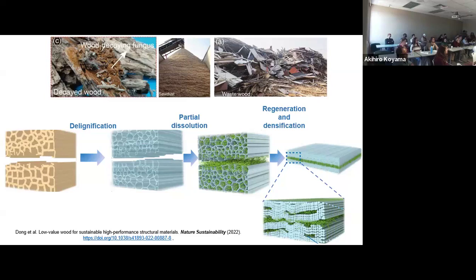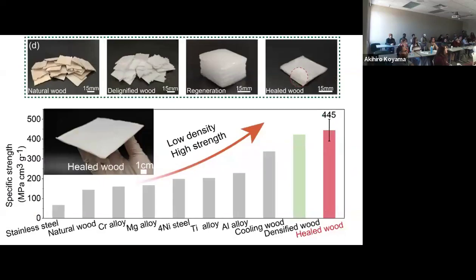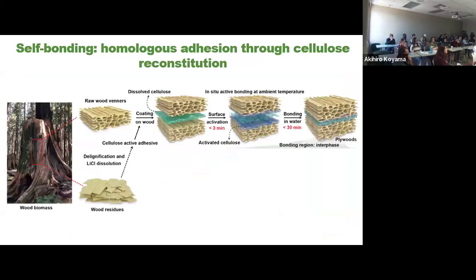We hydrate it, produce a hydrogel, and then by removing water, that drying really brings pieces together by capillary forces, and then you have the establishment of a very strong bonding. So we go back to a monolithic material, but in this case, very strong. And what we found is that the material actually achieves quite remarkable specific strength per unit density. That would be what we called at that time healed wood, here in red, compared to other materials that, again, per unit density, outcompetes many engineered materials. So it was a very simple idea, a concept that takes from the papermaking explanation that I gave earlier. Very simple. And that works.